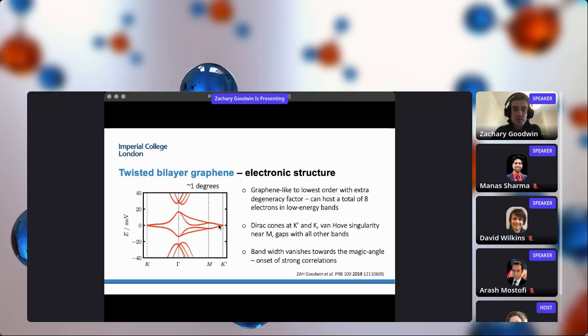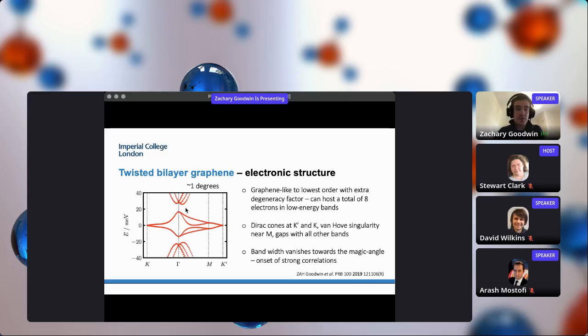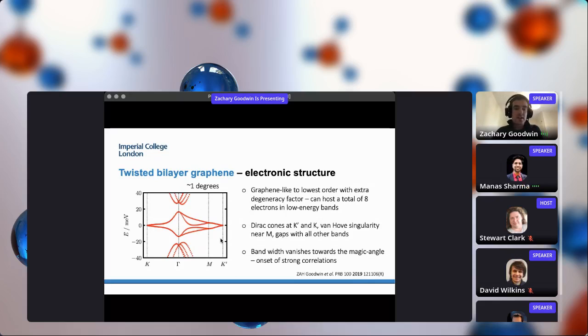So in this electronic structure, what we have is at the K and K prime points, there are Dirac cones. Closer to the M points, we have the Van Hove singularities. So this is quite similar to graphene. And then these flat bands have gaps between all the other bands as well. So they're energy separated from all the other states. And so the bandwidth of these flat electronic states vanishes towards the magic angle, which indicates that the kinetic energy of these electrons is going to vanish, and the dominant energy scale is going to be the electron interaction energy. And when that occurs, it suggests the onset of strongly correlated phases.